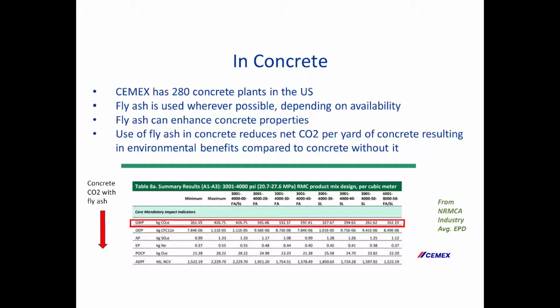But we've learned that it has very valuable properties to enhance concrete, such as sulfate resistance, which helps when concrete gets placed in soils that are high in sulfates, which can attack the concrete. It's resistant to that. It helps resist alkali silica reactivity. And what's really become more and more important now is the fact that when we replace cement with fly ash, we're reducing the CO2 per yard of concrete.